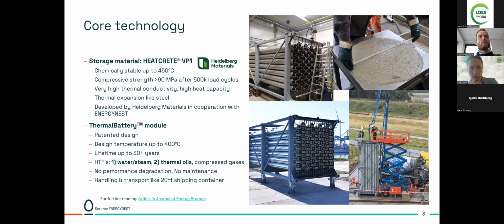This is a tailor-made thermal concrete that has been developed together with Heidelberg Materials, and they are fabricating and supplying this material. It's chemically stable up to 450 degrees Celsius, and it retains its very high compressive strength beyond 90 megapascals, even after 500,000 load cycles. It has a very high thermal conductivity and a high heat capacity. And it also has a thermal expansion which is very similar to that of steel.